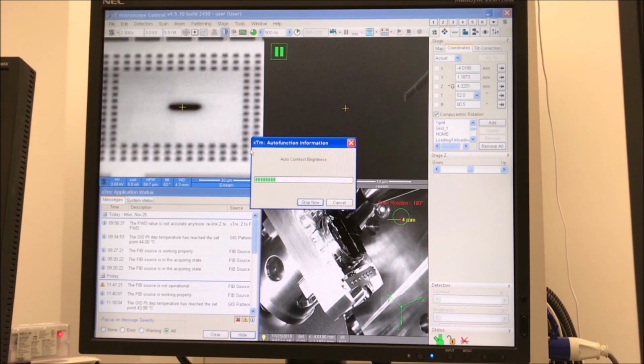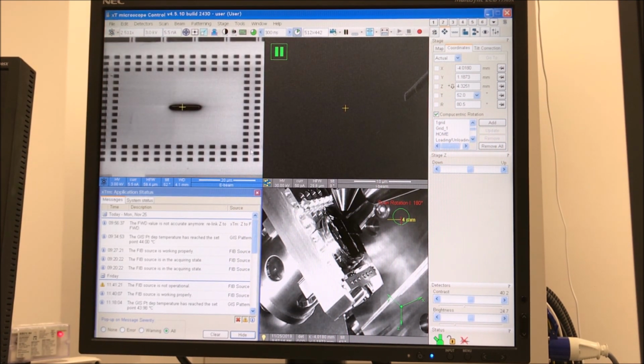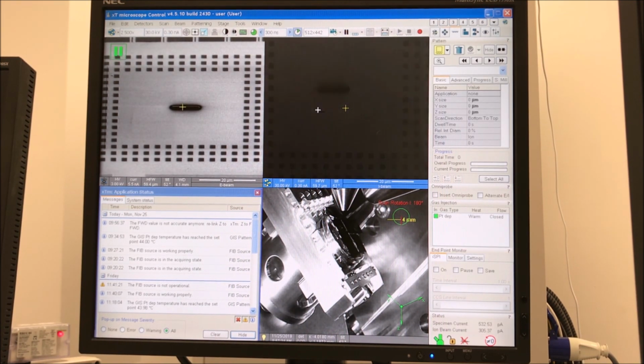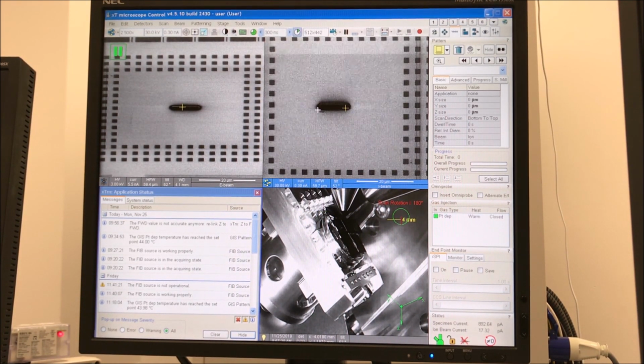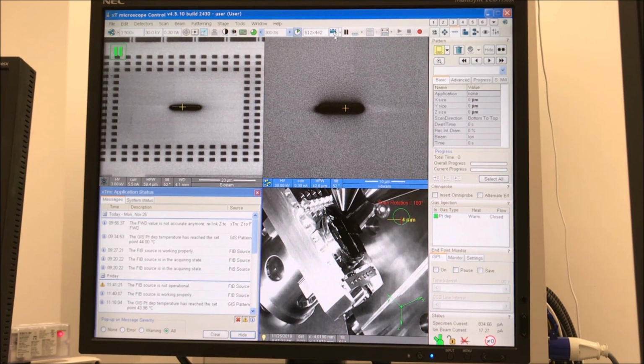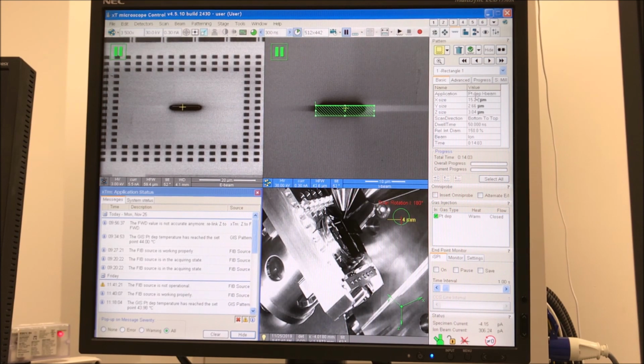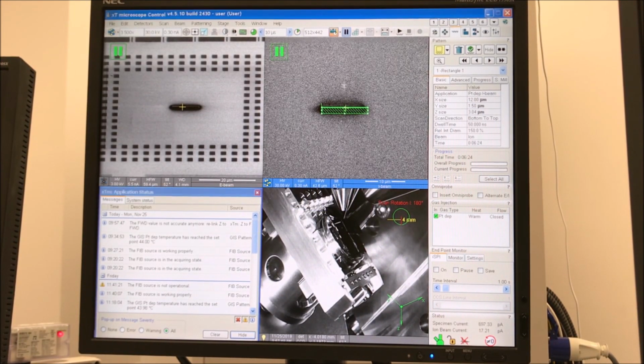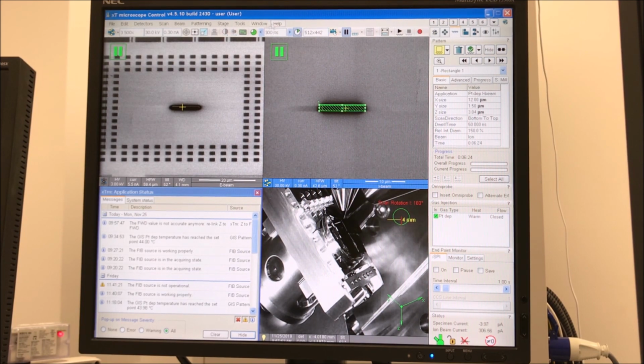So it moved a little bit from center, so again I can adjust that with the stage Z. Now I'm activating the I-beam quad, so I'm at 30 kilovolts and 0.3 nanoamps. You can go live and then use the shift knobs to center the strip in the image. And now we're going to define a rectangle pattern and deposit platinum using the I-beam.